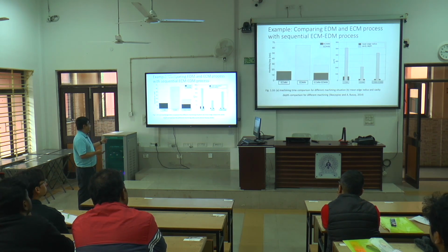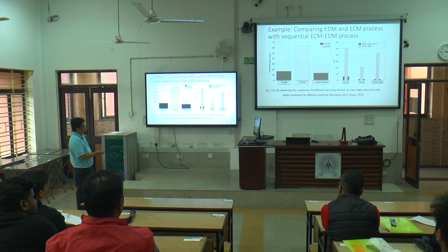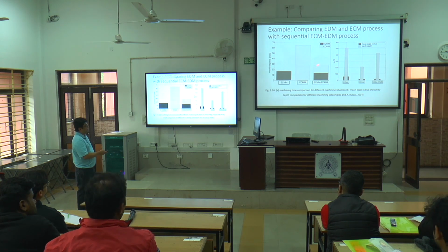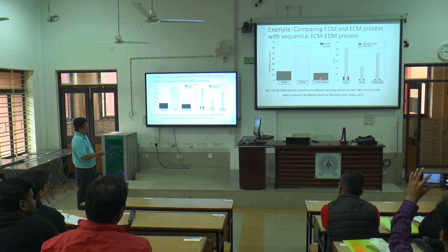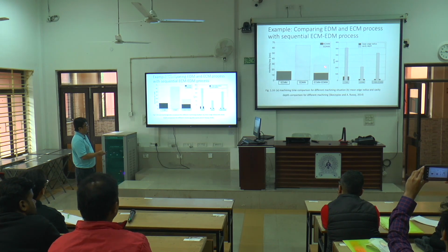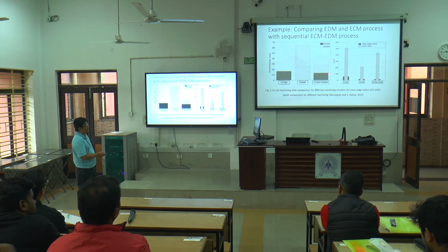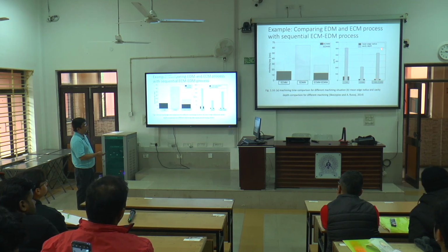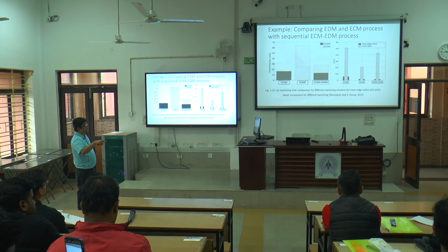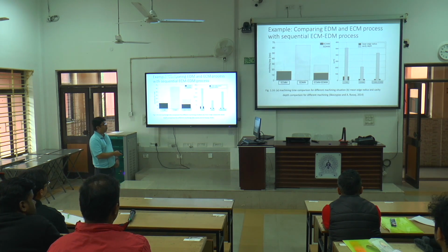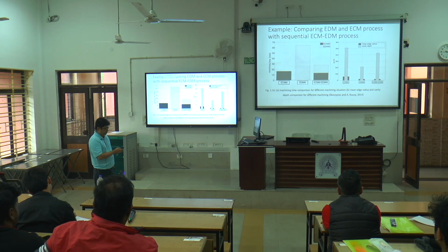Then this is just another example. If you are doing electrochemical micromachining and electro-discharge micromachining sequentially, one after another, it still helps in reducing the machining time for the finished part. Also, if you are using sequential processes, it can give you higher cavity depth with lower edge radius. Okay? Sometimes edge radius is difficult to control in the ECM process, so things become larger. But EDM you can control that, but if you use two processes simultaneously, it definitely is better.